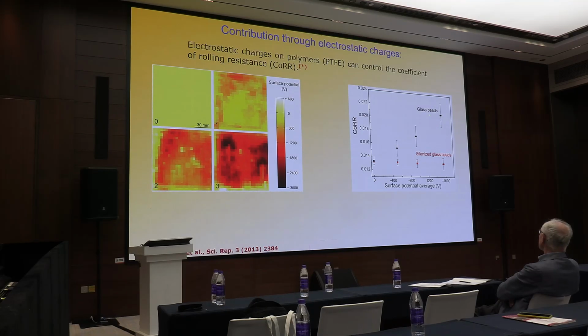In this case, these are balls of glass, and these are balls of glass but silanized. Here is silicon oxide, and here is silanized with silicon and hydrogen. It's not the same chemistry at the surface. What happened? Here you can see that this coefficient of rolling depends on the average surface potential. You have an interaction of the glass or silicon oxide with these charges. But when you have this silanized surface, this is silicon with hydrogen, it is independent. This ball of glass, silanized, cannot see the charge of the surface.